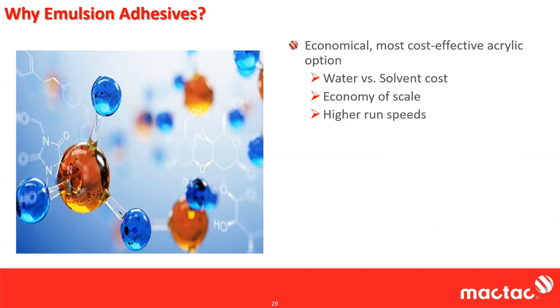Another thing here is economy of scale. A lot of your emulsion adhesives are based off the same raw materials that go into paint. Paint is far bigger in scale than pressure sensitive adhesives ever are, so you do get a lot of economy of scale there. And again, with your emulsion adhesives, depending on the thickness, you usually do get a lot higher run speed, especially on the roll label side. On the roll label side, those coaters can run 3,000-4,000 feet a minute. But again, you're talking very low coat weights, below 1 mil.